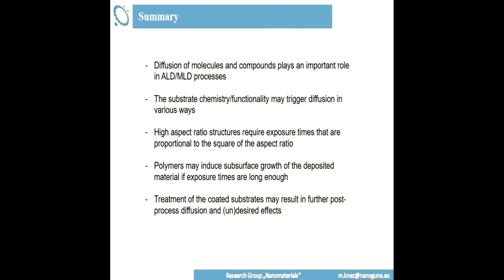So they decompose, they change. But if you do a post-treatment of your coated substrates, you may easily change your coating itself. It may be different crystallinity, different material which you generate, different porosity, different density. All of this. Again, diffusion phenomena play a big role.